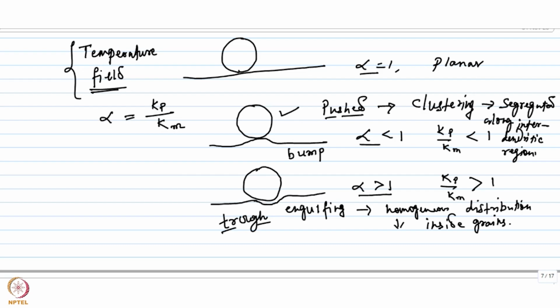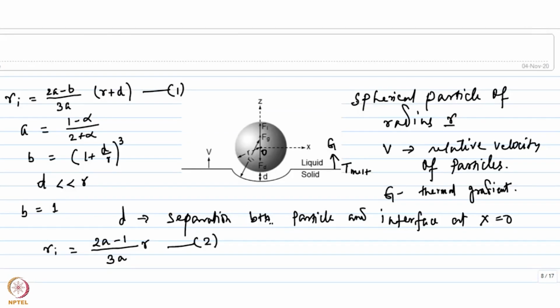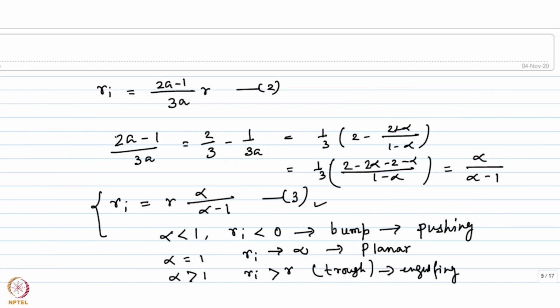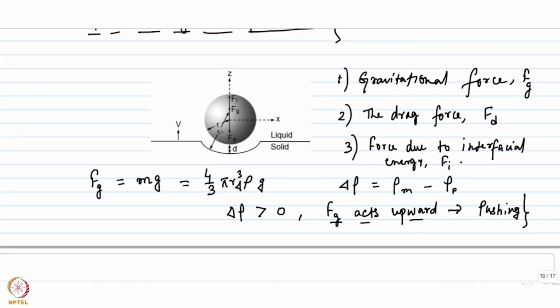Apart from this alpha, there is one more aspect that we considered, and that was the force acting on the particles. The forces which act on the particles also have a bearing on their distribution. Primarily there are three types of forces which act on a particle suspended in the liquid metal. These are the gravitational force, which is due to the weight of the particle, that is mg. Then you have the drag force, which is due to the relative motion between the particle and the liquid metal, and then the force due to interfacial energy. These three forces also have a bearing on the distribution of the particles in the composite material. How they affect the distribution, we have already discussed in the previous class.